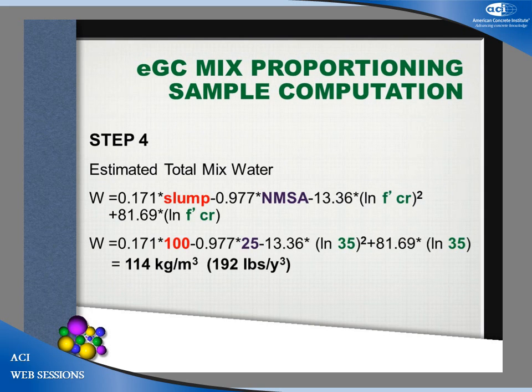Step 4. Use this statistical model. We know our slump, nominal maximum size. Just insert the slump value, nominal maximum size aggregate, and f'c value in this equation. By solving this equation, it will give the 114 kg per cubic meter water requirement, that is 192 pound per cubic yard. And if you design the Portland cement concrete with the same data, it would need at least 320 pound per cubic yard water.